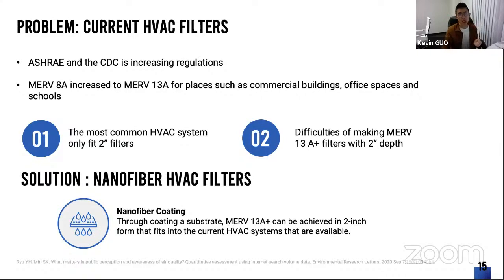The problem here is that most common current HVAC systems are built to fit only 2-inch depth filters. And it's extremely difficult to make MERV 13 filters with only 2-inch depth due to the high airflow resistance. In this case, nanofiber is a great solution for this problem due to the high filtration efficiency and the low pressure drop we mentioned earlier. By simply applying a thin layer of nanofiber coating, nanofiber enables the filters to achieve MERV 13 filtration performance without losing the 2-inch depth.